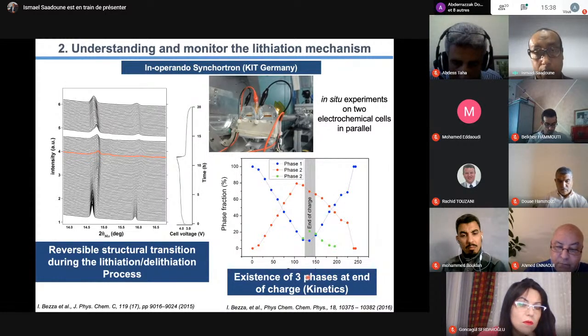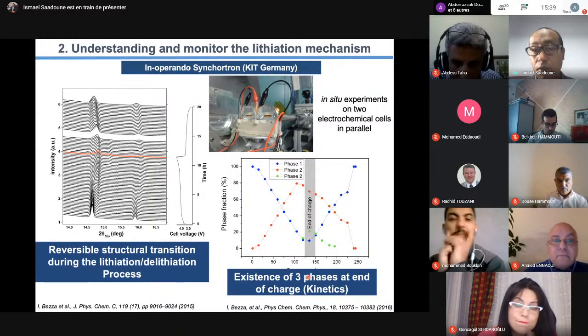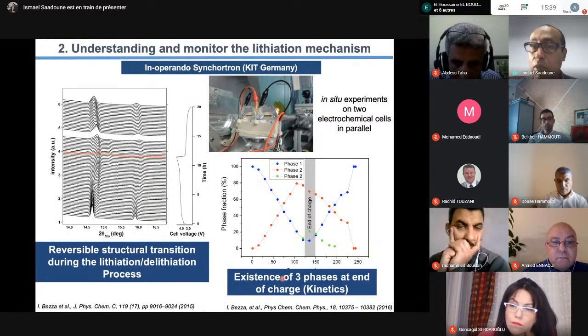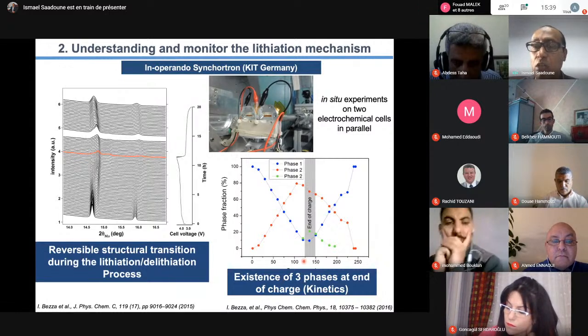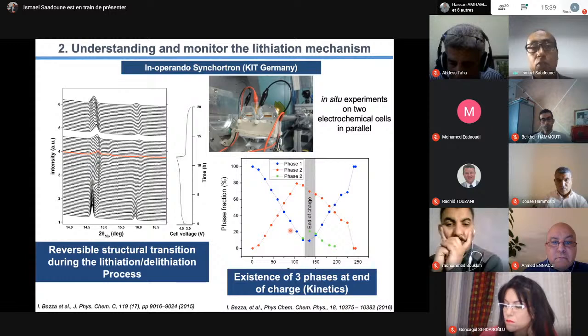This is really a good topic to understand what happened and to design new phosphate with porosity, with particle size, to have only 1 or 2 phases during cycling, during the charge or discharge process.